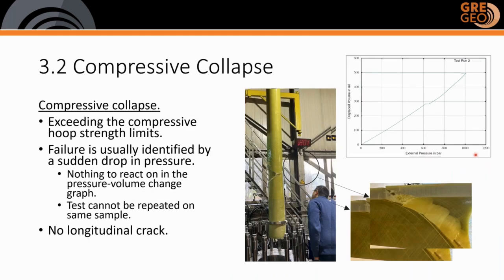So then, the compressive collapse. The compressive collapse is a sudden catastrophic failure that occurs when the stresses exceed the compressive hoop strength limit of the material. In the displacement volume versus external pressure plot, the event is shown as a sudden drop at the point of failure. You can see over here. Here the external pressure is plotted against the displacement volume. And the characteristic of this failure mode is typically severe damage to the pipe, like the delaminations as shown in this picture over here. And you can also see the type of damage that is indicated in the picture in the middle.